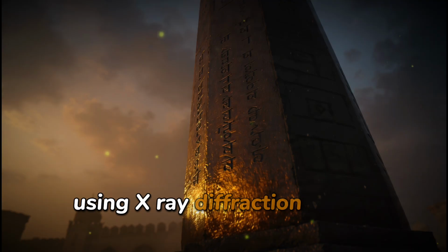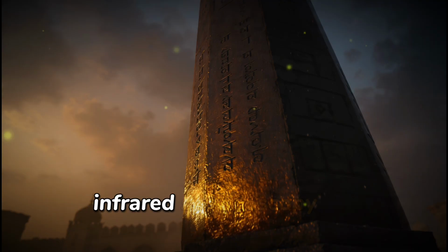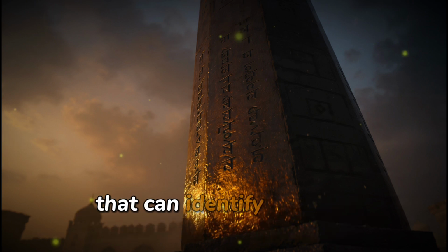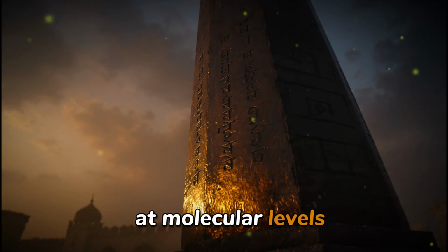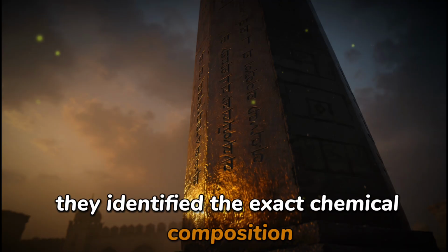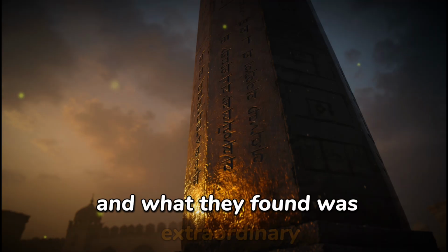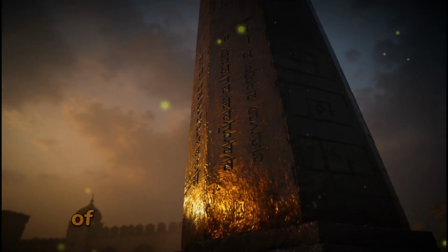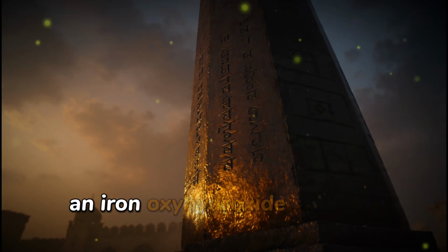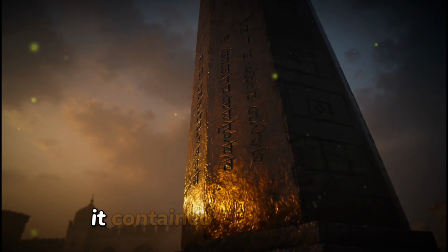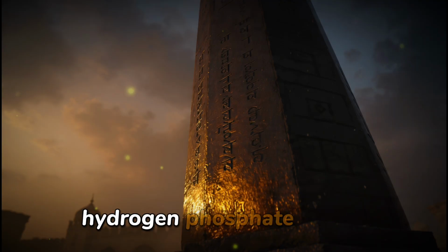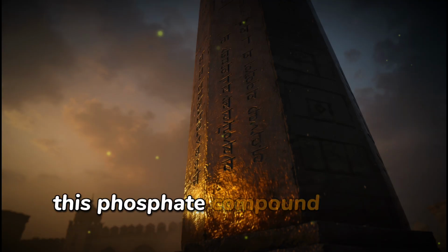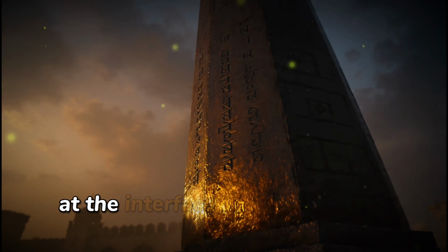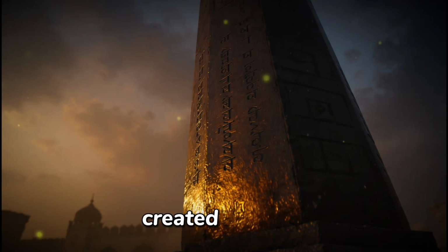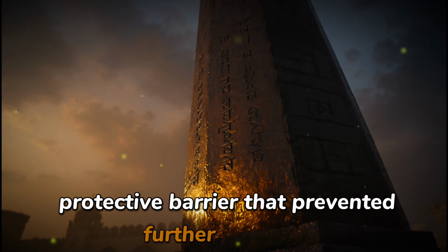Using X-ray diffraction, Fourier transform infrared spectroscopy, and Mössbauer spectroscopy, three sophisticated techniques that can identify chemical compounds at molecular levels, they identified the exact chemical composition of this protective film. And what they found was extraordinary. The film consisted primarily of a compound called misawite, an iron oxyhydroxide, but more importantly, it contained crystalline iron hydrogen phosphate hydrate. This phosphate compound, forming a continuous layer at the interface between the iron and the atmosphere, created a passive protective barrier that prevented further oxidation.